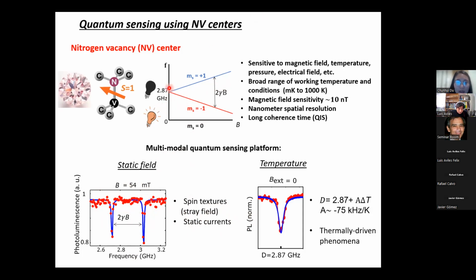If we measure the zero field splitting frequency, it couples with the lattice constant of the diamond lattice. So this enables sensing of the temperature using NV center. The zero field splitting frequency of NV center will change with the external temperature in a well-known fashion. So this allows us to also study thermally driven phenomena, for instance, spin caloritronics or other thermally driven phenomena based on NV center.